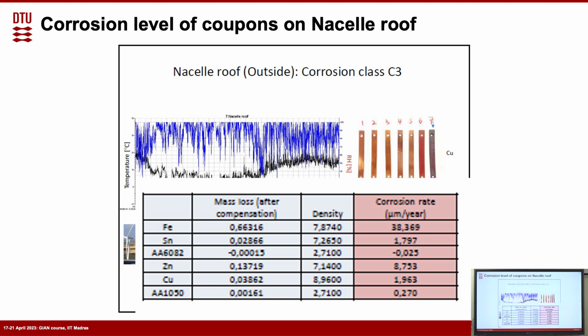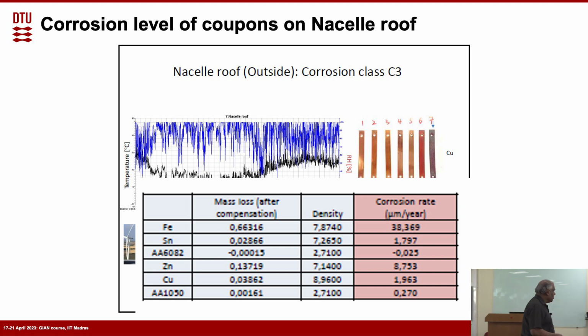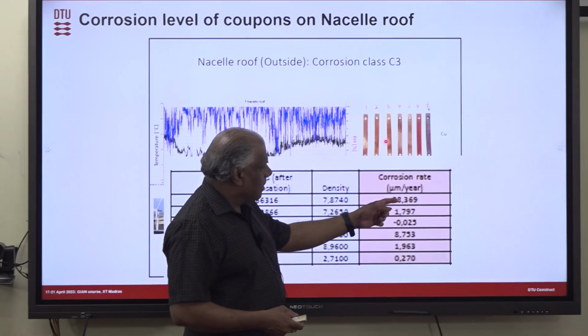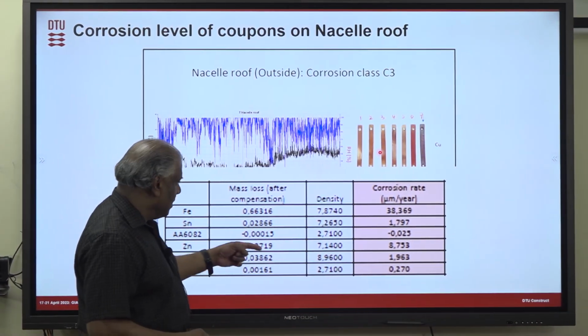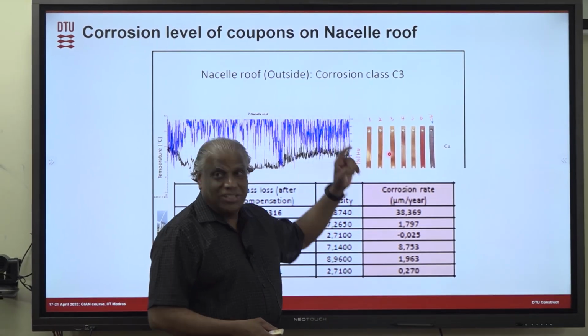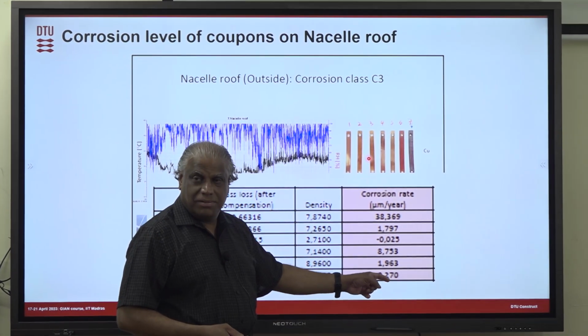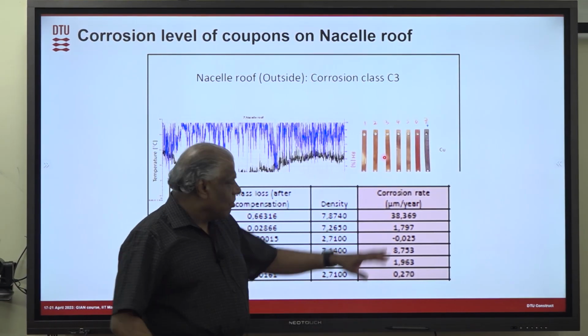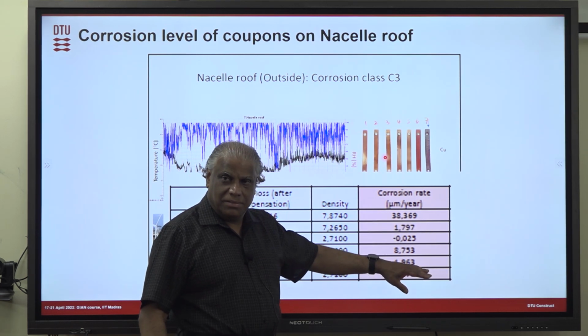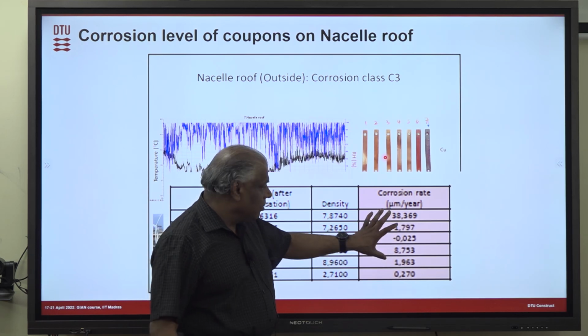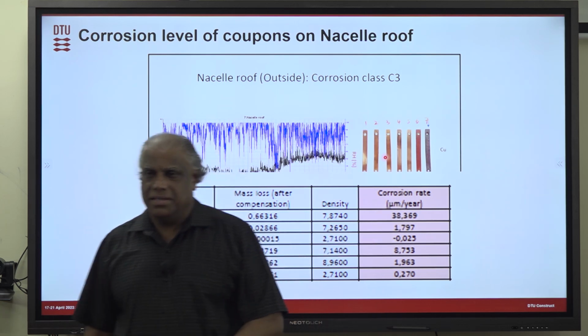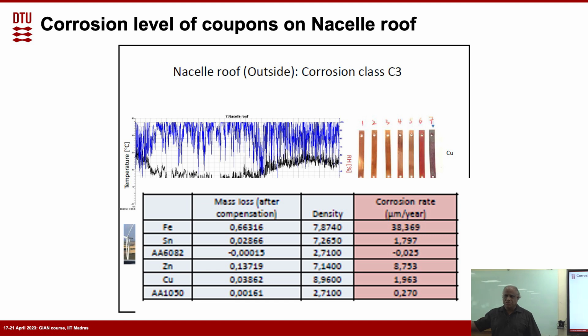That is for each material, not everything, but for example, iron. People have done the experiment and classified it into C1, C2. Similarly for zinc, there is a corrosion class and everything. So all these are based on that. If you look here at the copper, iron, the distribution of iron, the distribution of zinc, based on all these it is approximately the C3 class. So everything is considered here. Put another way, in the C3 class, corrosion of iron will be higher compared to corrosion of zinc. Corrosion of zinc will be lower in the C3 class. In the C1 class also the ratio will remain almost the same. So based on all of them, it is coming to the C3 class. That's the idea. It is just compared with atmospheric corrosion data where it is classified into the C1 to C5 levels. Approximately, I'm not saying that it is certainly matched with that, but that way it is classified as C3. Is that what you're asking?